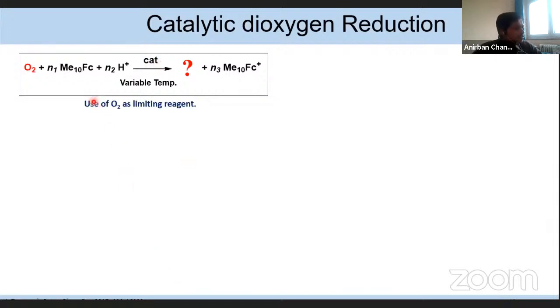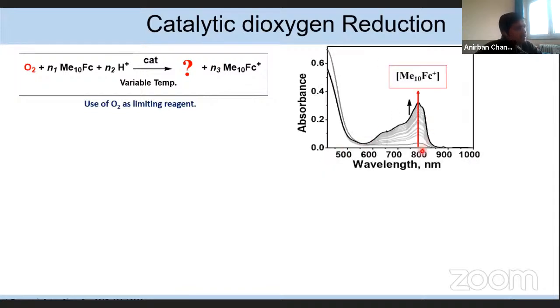For this we use the Fukuzumi method. This method was introduced by Fukuzumi, where, instead of an electrochemical method, you can check the oxygen reduction reaction via UV-vis. In this method we have to use a source of electron, where here I use decamethylferrocene as the electron source, and as proton source I use trifluoroacetic acid or triflic acid. In presence of electron and proton, my complex is set to react with the oxygen. What I found is that as the reaction proceeds, one new band starts generating at 780 nanometer, which corresponds to the decamethylferrocenium ion.